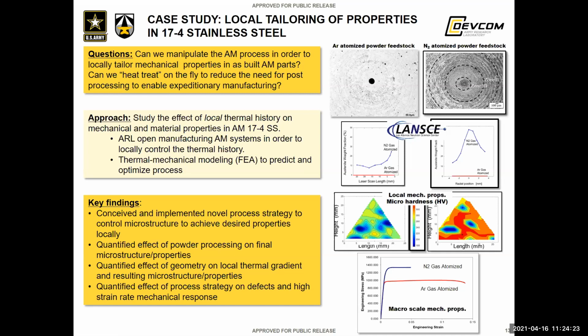This is the work into local tailoring of process-property relations within 17-4 stainless steel. For this, we're utilizing the ability that we have on an open manufacturing system, so we're able to control the first order processing parameters, among many others, like the speed, the thickness, the hatch spacing, and the power on the fly. We're trying to see how we can utilize this to affect, say, mechanical material properties locally, so that maybe we can reduce the need for heat treatment, for example.